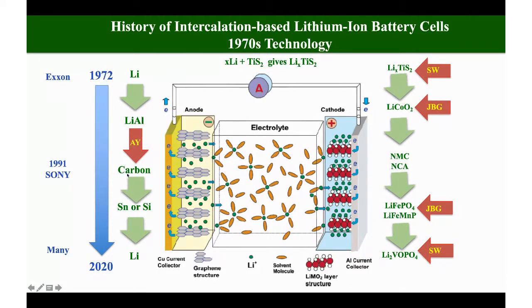By that time, John Goodenough, who had read our paper on TiS2, was looking at magnetic behavior of cobalt oxide, decided this had the same structure, and he then developed this as a battery whilst in Britain, and the Atomic Energy Authority owned the patents on this material. Subsequently, most of the cobalt has been removed and replaced by nickel and manganese. And in the case of Tesla, they use nickel, cobalt, and aluminum. So this is the commercial system.